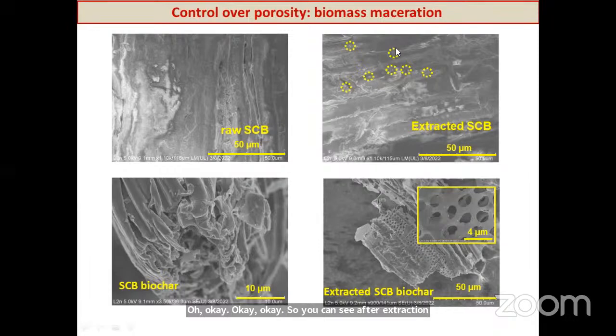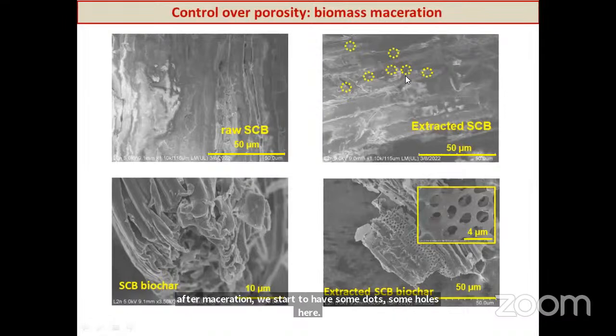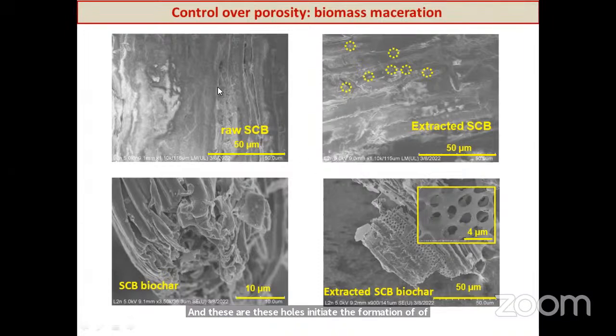So you can see after maceration, we start to have some dots, some holes here, and these holes initiate the formation of porous structure of biochar. For the biochar after maceration, we obtained an increase in the surface area from about 270 square meters per gram up to 350 or 360 square meters per gram. Okay, it's not 1,000 or 2,000 square meters per gram as claimed by some groups when they treat with KOH or with phosphoric acid, but at least we have a green way to obtain some porous structure.